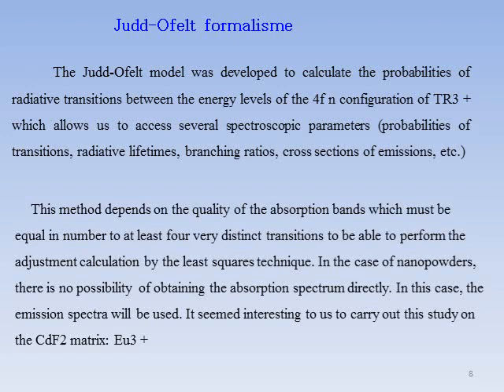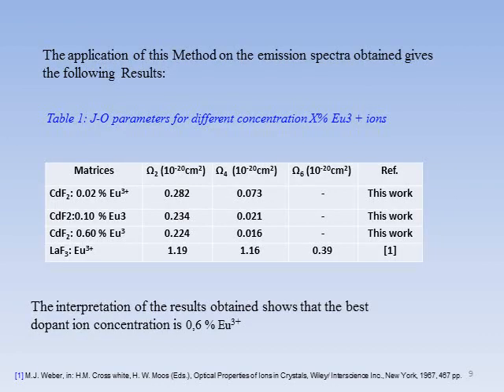This method depends on the quality of absorption bands, which must be equal in number to at least four very distinct transitions to be able to perform the adjustment calculation by the least squares technique. In the case of nanopowders, there is no possibility of obtaining the absorption spectrum directly. In this case, the emission spectra will be used. It seemed interesting to us to carry out this study on the CdF2 host matrix doped with europium ions. The application of this method on the emission spectra obtained gives the following results. The interpretation of the results obtained shows that the best dopant concentration is 0.6% of europium ions.